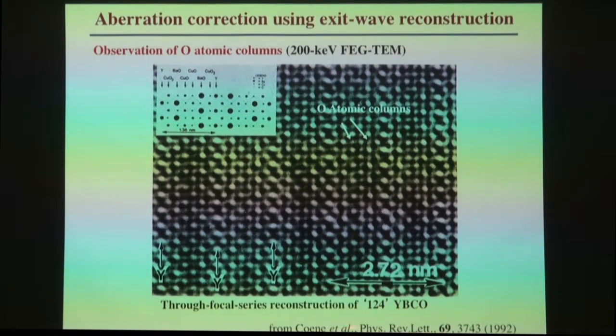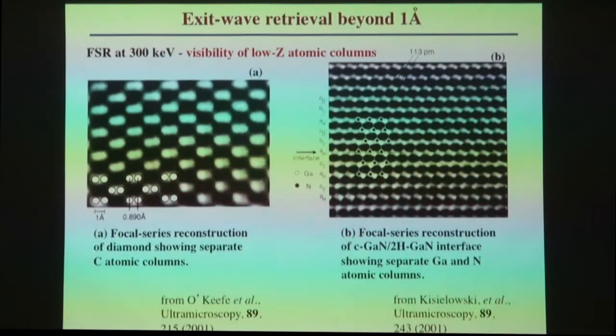Okay, so this is from the work of Coene, 1992, where he did an exit wave reconstruction. They took 32 images, changing the focus successively, and in this particular case they could see oxygen atomic columns for the first time. The microscope's structural resolution was 2.4 angstroms, but the information limit was 1.4 angstroms, and by doing this exit wave reconstruction, they were able to see all of the oxygen atoms in projection.